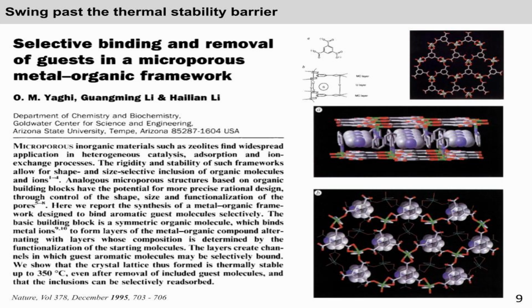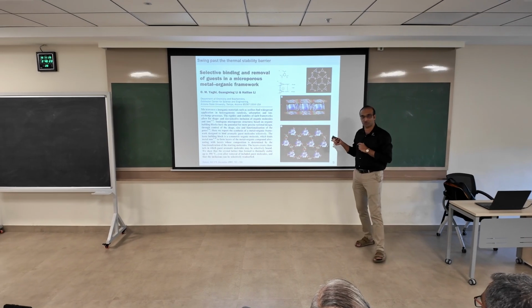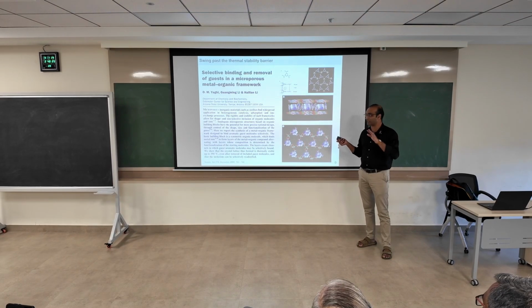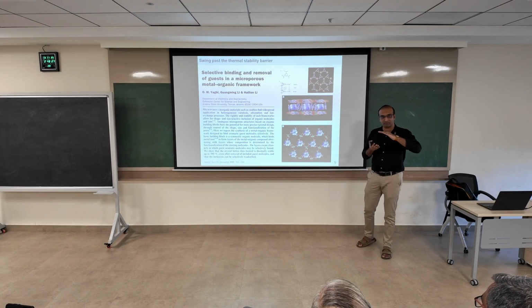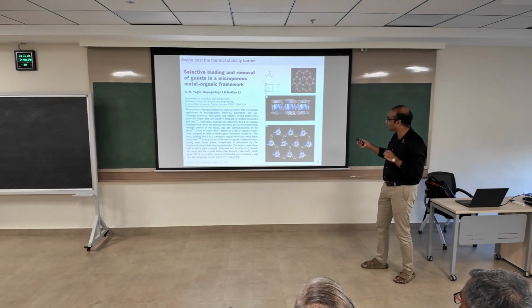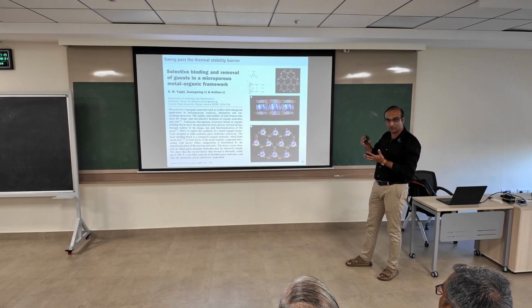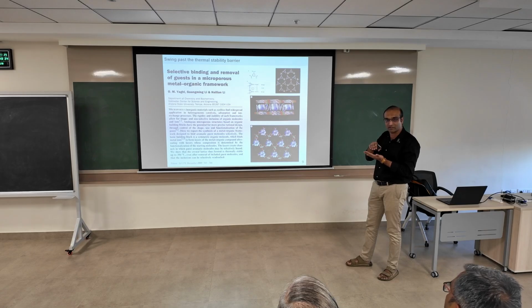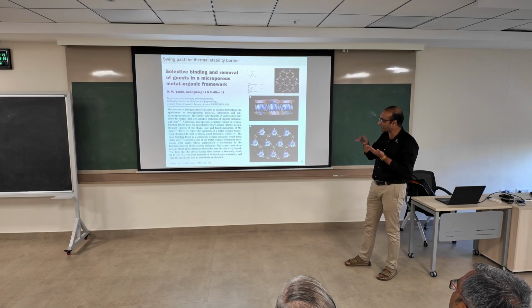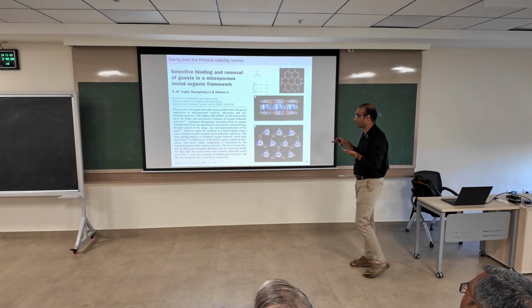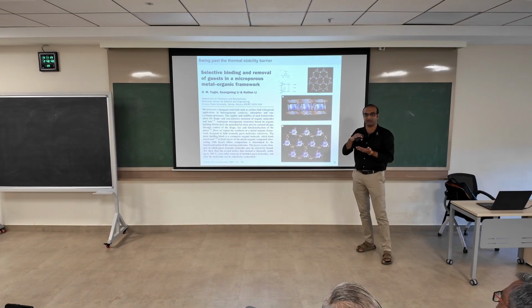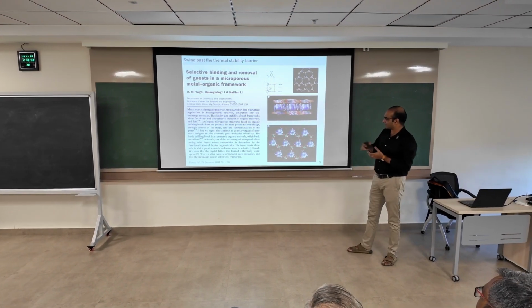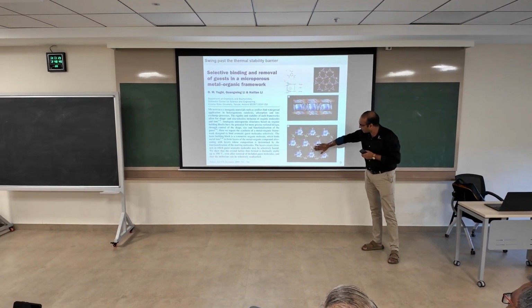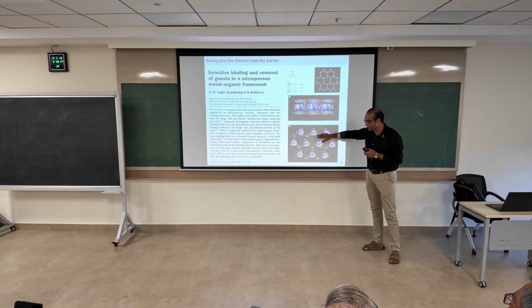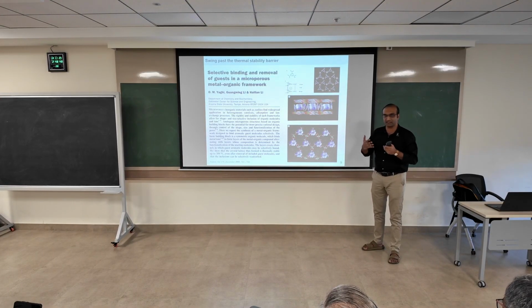Okay? And the good thing about this kind of structure, it could selectively hold only aromatic compounds, no aliphatic compounds. So if you put an aromatic compound into it, because of pi stacking between these two layers, you can have this pyridine or some other aromatic compound held in between. You can separate aromatic compounds from aliphatic compounds, as long as you had some kind of pi stacking. Okay, so this is the top view of the same thing. You have a top layer, then you have pyridine in between this layer and another layer, and you can trap them like that.